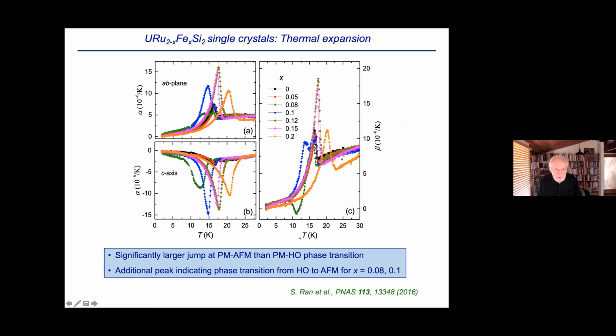Okay, these are some thermal expansion measurements, in the a-b plane and along the c-axis. Again, you can see features due to the hidden order phase and the antiferromagnetic phase. This is the volume thermal expansion deduced from these data right here. And there are significantly larger jumps at the paramagnetic to antiferromagnetic phase transition than at the paramagnetic to hidden order phase transition in these data. You can see that here.